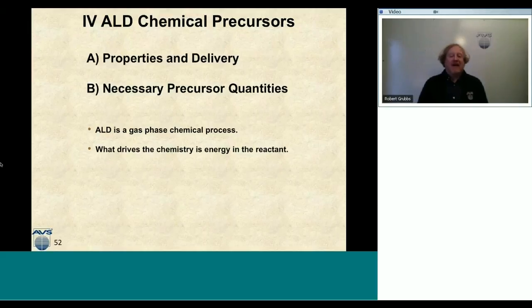So we know that ALD is a gas-phase process, but what drives the ALD process is the energy that's in the reactant. If I can build a reactant that's very energetic, that's also probably very toxic and very pyrophoric, it's probably an excellent chemical precursor for ALD because it drives the temperature down. So we really want to build all the chemical energy into the precursor molecules so that we can perform the ALD chemistry on the surface. That's why chemical precursors are a unique and growing area of ALD research. So let's take a look.